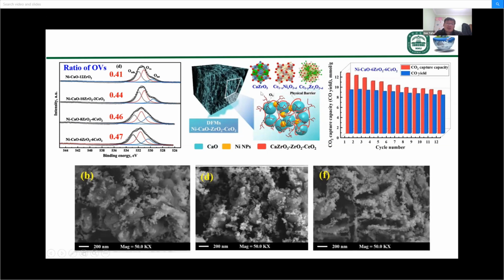In addition, the calcium oxide also interacts with the zirconium oxide to form this solution, which acts as a stable physical barrier to prevent crystal sintering and particle accumulation, which also improves its working stability. And the SEM image shows that Ni particles are uniformly dispersed on the surface of the sorbent. And this will also be favorable for its CO2 conversion.